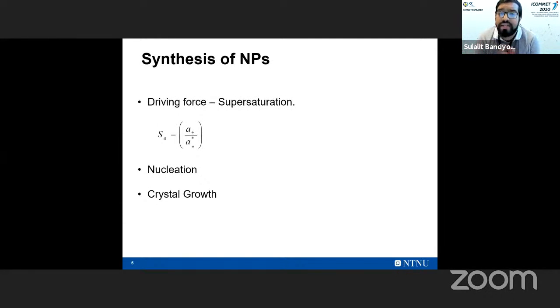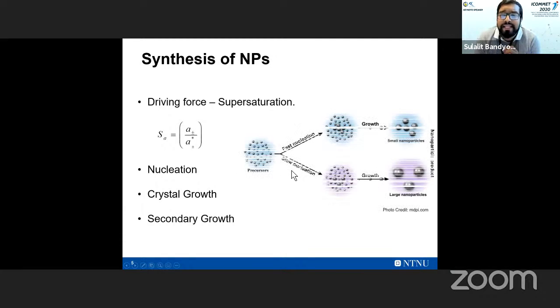And then the nuclei would start to grow by a fundamental process of crystal growth. Whether you go through a classical or a non-classical approach is not the point of interest right now, but the particles will enlarge or grow in size. And then additional growth continues, which we refer to as secondary growth or size enlargement through different processes such as Ostwald ripening, and so on. If you want to schematically visualize what's happening, you generate precursor materials, especially for reactions that require a preceding step to generate supersaturation, most likely a reduction process. If you have a fast nucleation, it would result in small nanoparticles, whereas if you have a slow nucleation, you will get bigger nanoparticles. Having said that, I would like to caution you that this is not the only criterion that controls the nanoparticle size, but one of the most important.